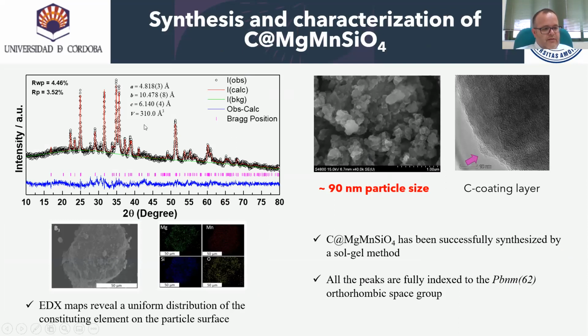The sample is characterized by crystalline, well-shaped nanoparticles of around 90 nanometers with good uniformity. A close inspection by TEM reveals that carbon is uniformly coated on the particle surface. The small particle size is beneficial for ion diffusion, and a homogeneous carbon coating would facilitate the electron transportation. EDX maps reveal a uniform distribution of the constituting elements on the particle surface.